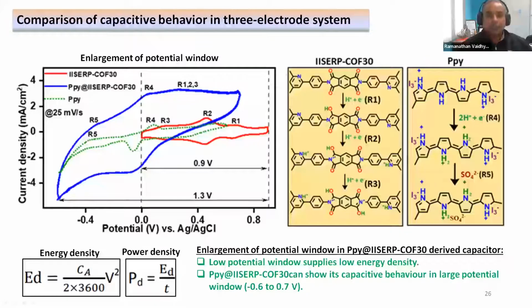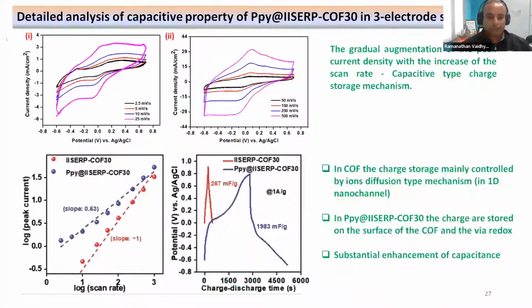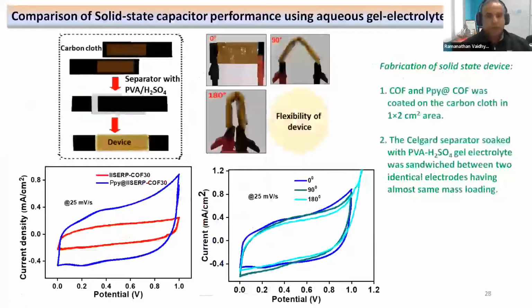Can we do this with this composite material? So before I go to that, we can also see from the 3 electrode measurements, there's a true capacitive behavior from the variable scan rates. And also you can see there's a strong enhancement in the capacitance when you go from the neat COF to the composite material. And the enhancement is almost 10 folds.